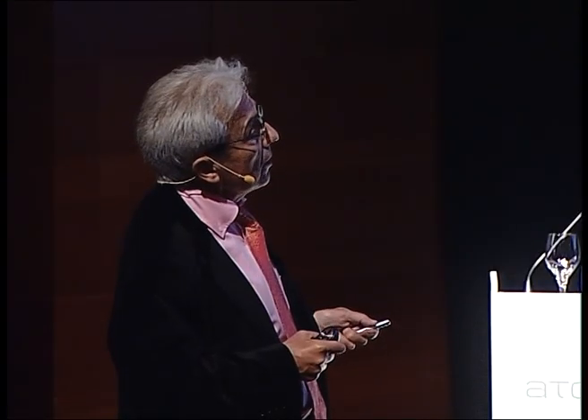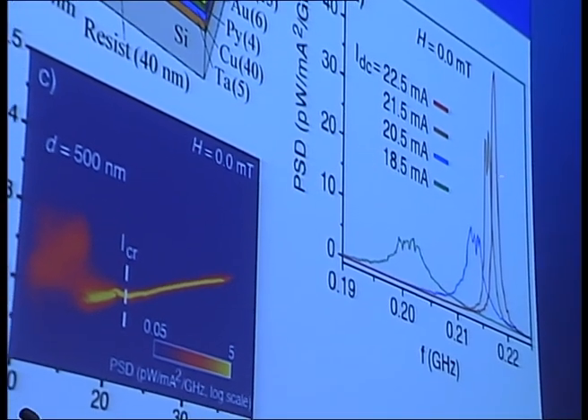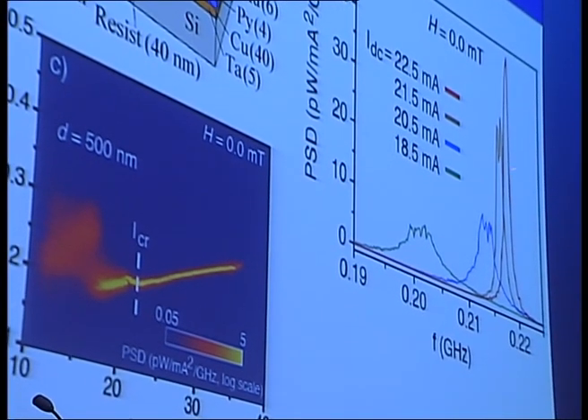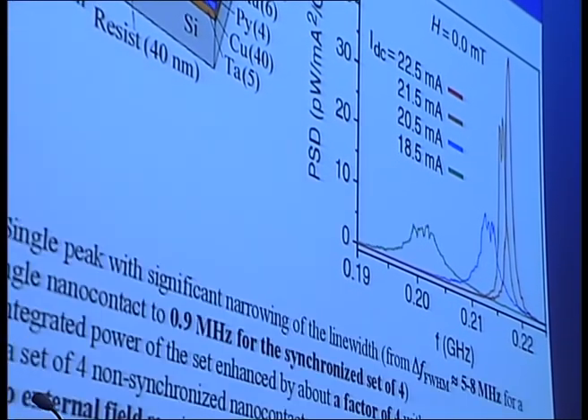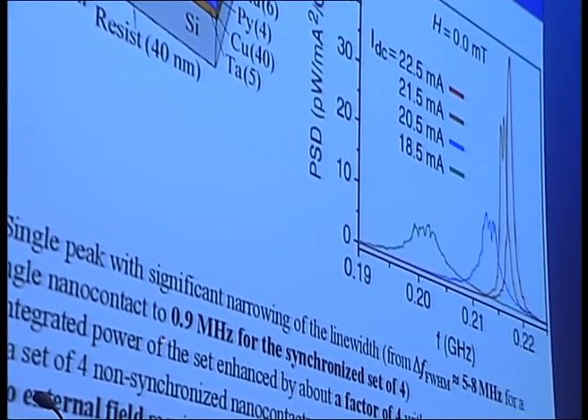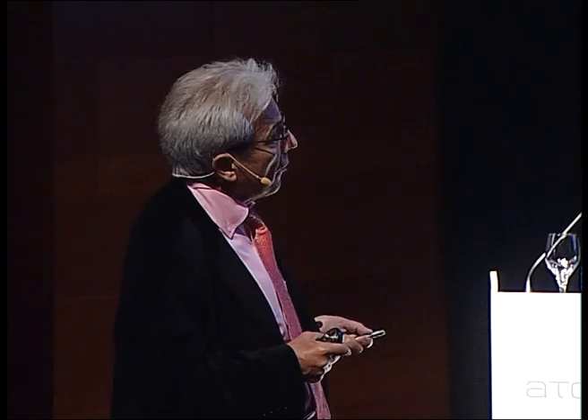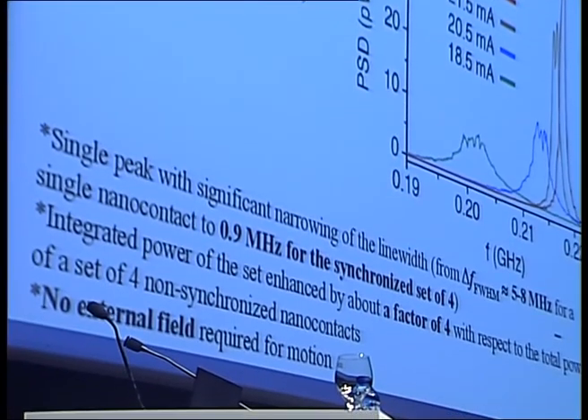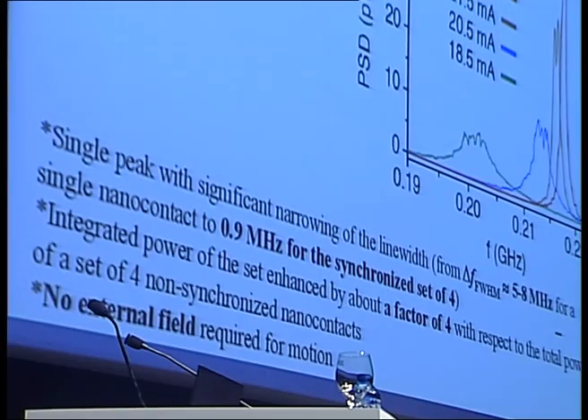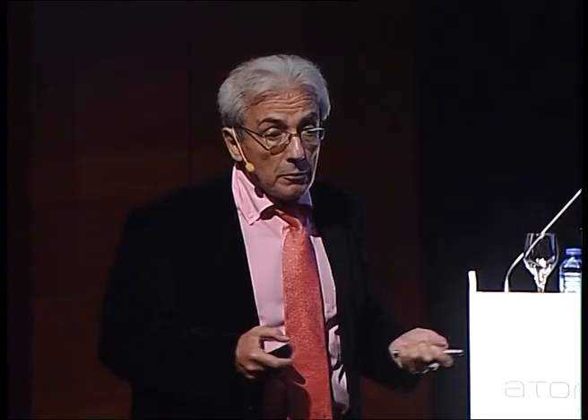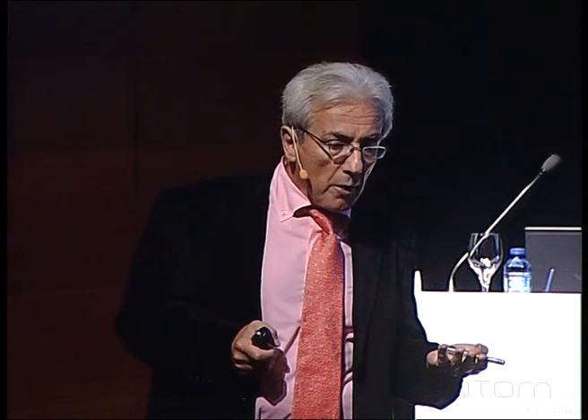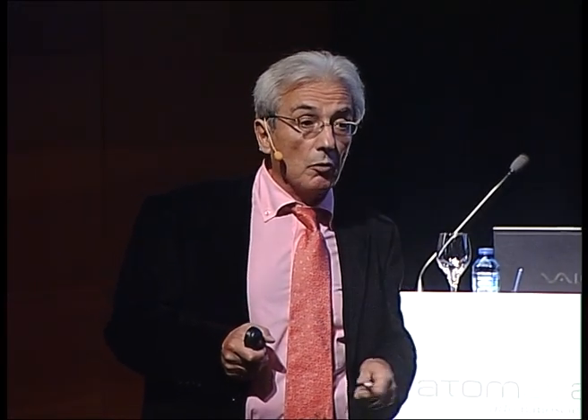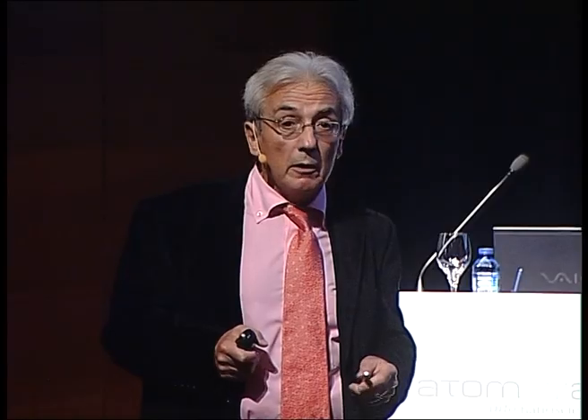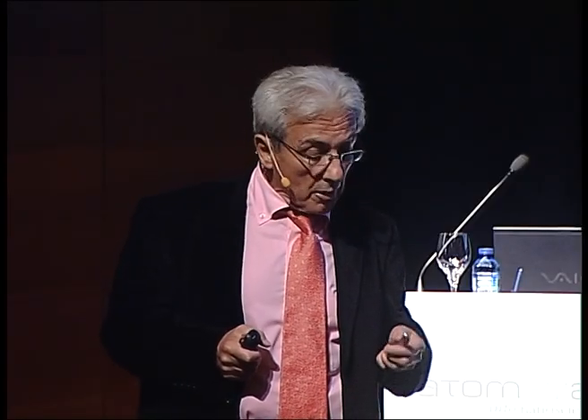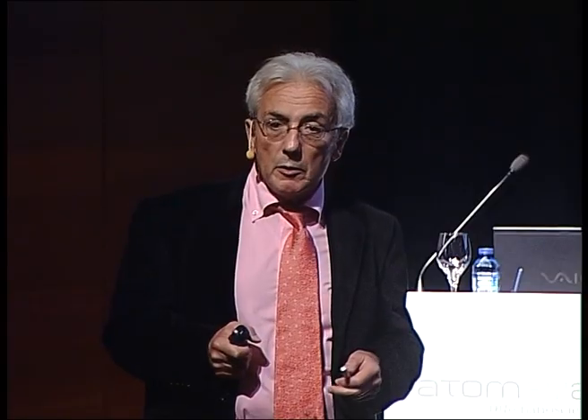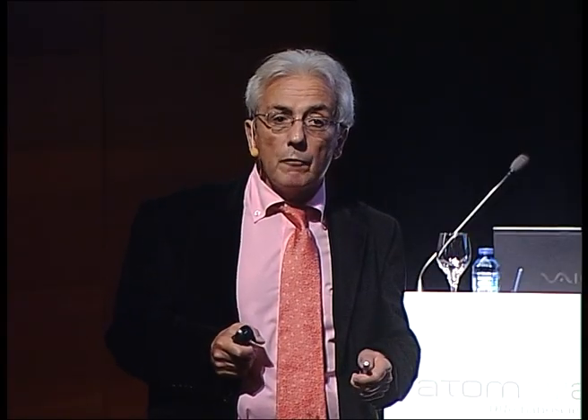That is, you can see this line progressively emerge into 2 lines, and finally in a single line with a larger power and a very narrow line this time. In fact, the decrease in the width is significant. The width becomes smaller than 1 megahertz, and there is also a significant increase of the power by synchronization. Finally, you see, this is a domain in spintronics that is improving, advancing rapidly. I suppose that in simply, say, 4 or 5 years, there will be a telecommunication device based on this type of oscillator.